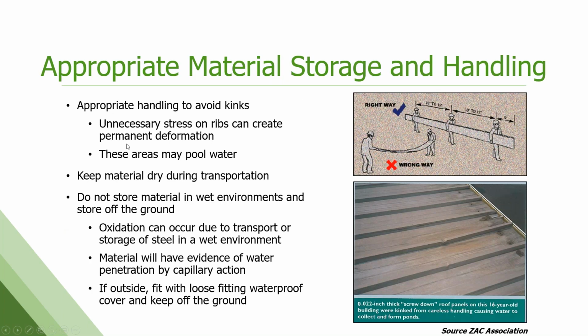Storage on site is important. This is really for the installers, to avoid bending or kinking the panels. You also want to store it so that water can't pool or sit on it in the bundles or stacks. We call that wet stack corrosion or storage corrosion. It can happen very, very quickly, believe it or not, in a matter of days if it's very wet. So you've got to get it out and expose it to air as quickly as possible.